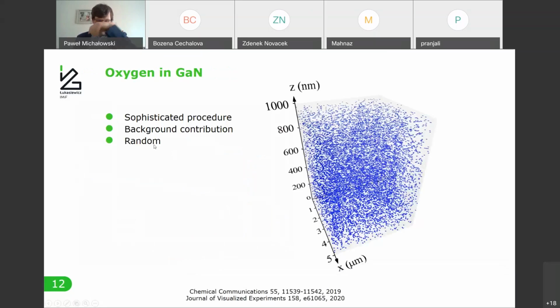Okay, now let's change to a much thicker sample. In this case, gallium nitride, this is a very sophisticated procedure. I spent a lot of time to develop it. Basically, what I wanted to see is the unintentional distribution of oxygen contaminant in gallium nitride material. So this is the result, and you may say, okay, you said you spent a lot of time, but there is nothing special about it. Basically, you see a very random distribution of oxygen counts in this